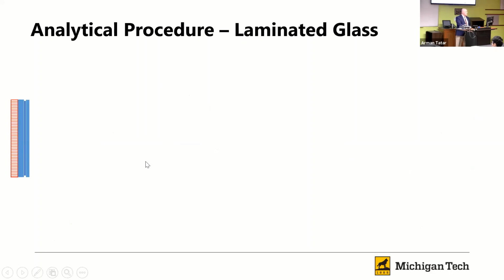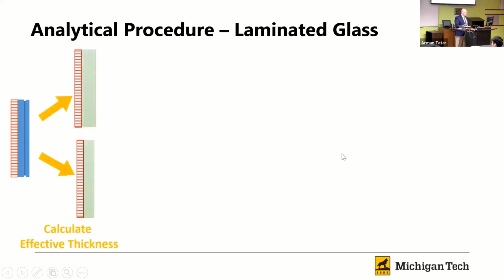For laminated glass, in this case we have two methodologies that the standard allows you to use. One is the effective thickness model. Because layered plate analysis is somewhat complicated and we need to be able to model that inner layer appropriately, you have to have a fairly sophisticated FEA package in order to do that accurately. And it also tends to take a while as far as doing the calculation.